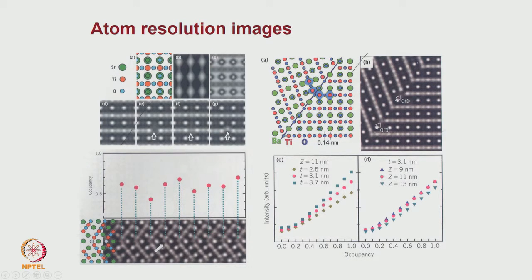In another one you can see that this atom has slightly shifted, which means the position of the atoms in the image could be measured very accurately. Especially here we know that barium titanate, when it exhibits the piezoelectric effect, has a tetragonal distortion introduced to the crystal structure. So, the shift of the atom positions could be measured accurately.